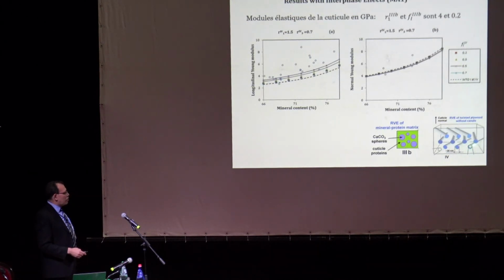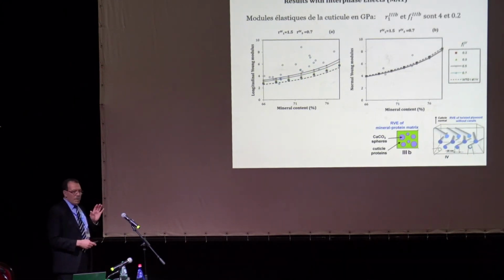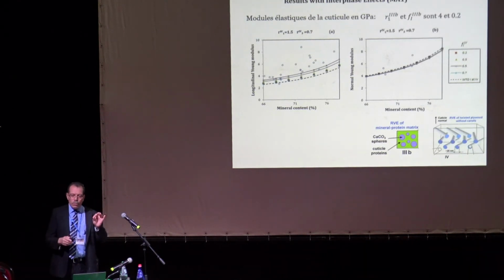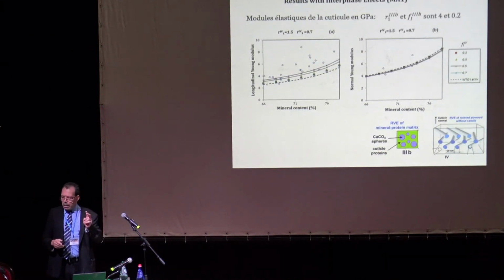However, at this level, the change was not much. Actually, the interfaces did not give us much change. However, at this level, when we include an interface between the calcium carbonate spheres and the matrix, then there is an important effect, okay? And by doing so, here is what we get. For the normal Young's modulus, which initially was already not too far off, there is not much difference in the different cases we looked at. And for longitudinal, we are getting much better results. However, we really have to tune these results in terms of the ratio between the properties of the filler or the matrix and the interface, okay? And also the amount, or the volume fraction, of that interface. We have no idea, so we just use tuning somehow.